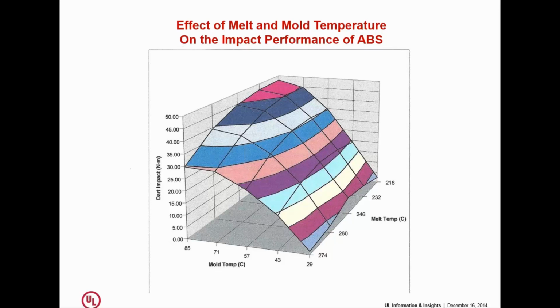So a warm mold and a cool melt produce a very, very tough part. A cold mold and a hot melt produce a material with very, very little of the impact that the material is intended to have. So there's a great deal at stake here in being able to set your machine up the right way so that the material gets treated the way it wants to be treated. And all this starts, remember, with having a machine that can develop enough pressure so that you can drive the material at the right speed so that you do not have to over-rely on temperature to get the viscosity you need.